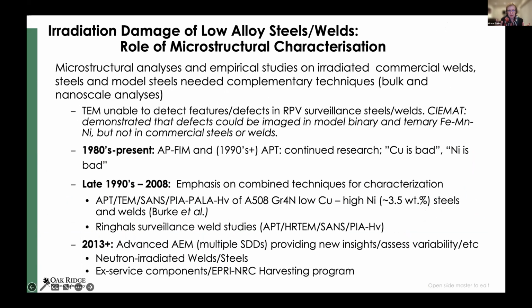There was interest in this field for quite a long time, and in pure metals and certain model systems like binary alloys, it was possible to do a lot of excellent work looking at TEM analyses of defects. However, in the real materials that we have to deal with, TEM was not able to identify or detect any of these classic irradiation-induced defects. So starting in the early 1980s through the present, atom probe field ion microscopy, and beyond that atom probe tomography, the local electrode atom probe and the EcoPoSAP continued.